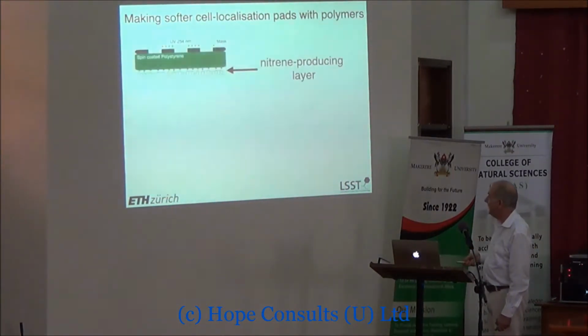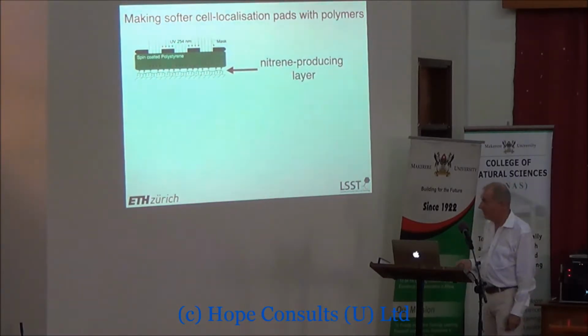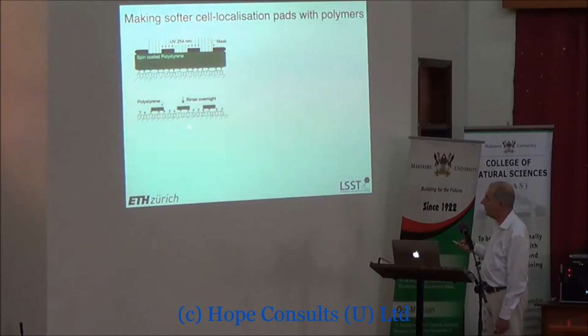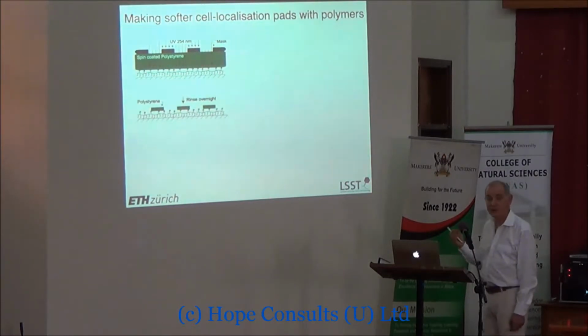Now, another way of making patterns also uses photolithography, but it's doing it with polymers. So here we're using our nitrenes that I told you about earlier. We put down our nitrene generating layer, we spin coat polystyrene on top of it, and then we put a mask on top of that to pattern the UV light that we then shine through. The UV comes through, activates the nitrenes here, they stick onto the polystyrene. In this area, we don't activate them, so they don't stick. Then we wash it, and all the polymer comes off except the chains that were in close contact with the nitrenes that saw the UV light.